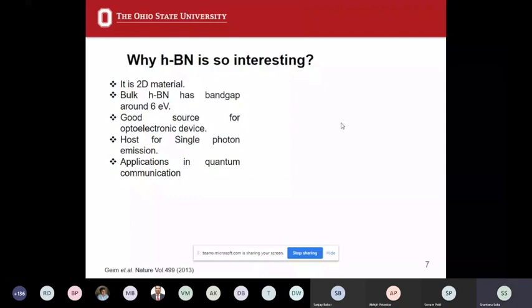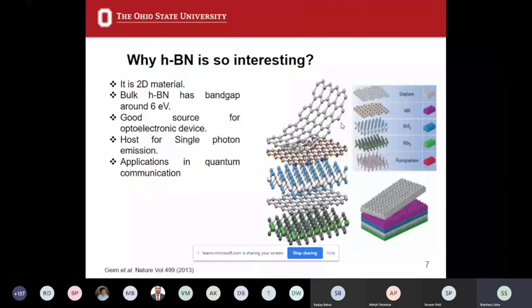hBN is also called white graphite. So I can show you one more figure. You can see these are all two-dimensional structures. You can see graphene, you have hBN, MoS2, molybdenum disulfide, and WSe2, that is tungsten diselenide. So hBN is also known as white graphite, and it's a van der Waals material, which means that in-plane bonding is very, very strong compared to out-of-plane bonding.